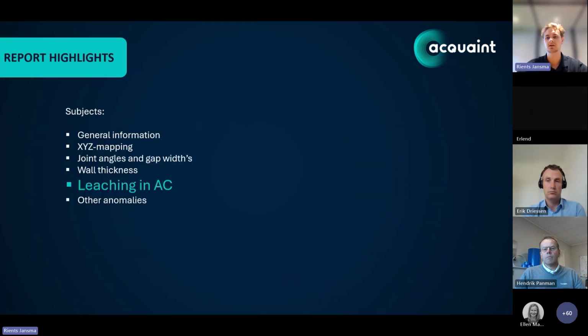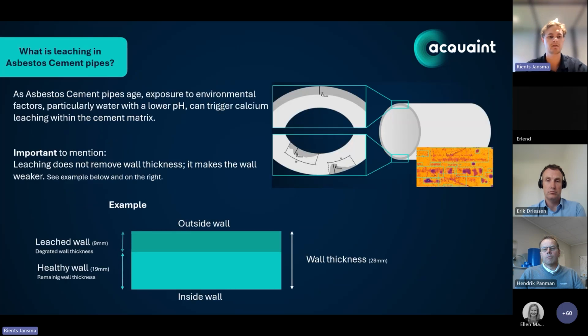Okay, over to leaching in asbestos cement. As asbestos cement pipes age, exposure to environmental factors, particularly water with a lower pH, can trigger calcium leaching within the cement matrix. You can see it on the picture on the right side. Those are some leaching spots. It's important to mention that leaching does not remove the wall thickness. It just makes the wall weaker. On the example below, you can see on the right side, the wall thickness for this example is 28 millimeters, and the leached wall is 9 millimeters, and the healthy wall is 19 millimeters.